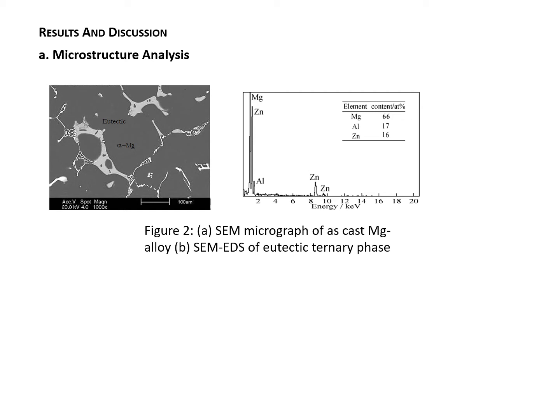However, the EDAX result as shown in figure 2b confirms the presence of a ternary intermetallic phase of Mg-Zn-Al having the ratio of 66, 16 and 17. It is further noticed that this ternary intermetallic phase ratio varies with different locations in the microstructure of the MgZnAl type.